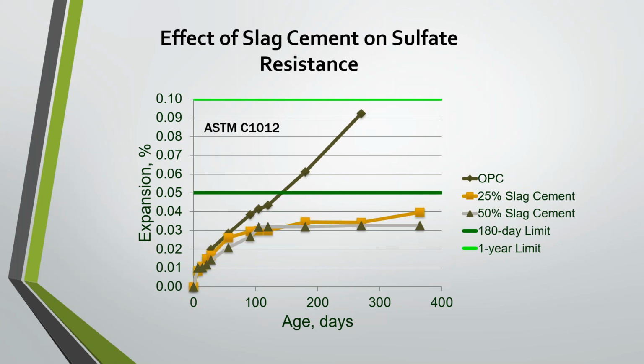And then you have two scenarios of slag cement replacement. You can see the specification limit. In this case they're putting this against a 1-year limit and a half-year, or 180 day, limit. You can see that even the introduction of 25% slag cement gives a substantial reduction in the expansion due to sulfate, and that's because you have less of the C3A component, you have lower permeability, and you have other things driving that expansion rate down. Next slide.